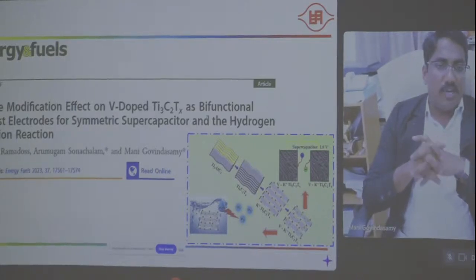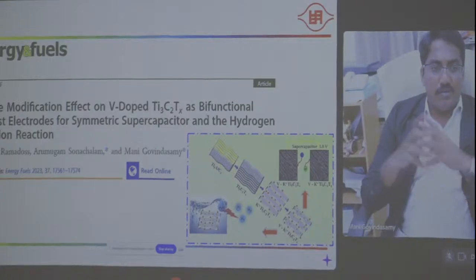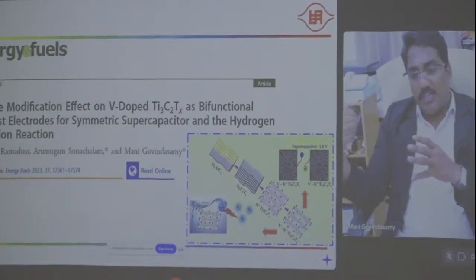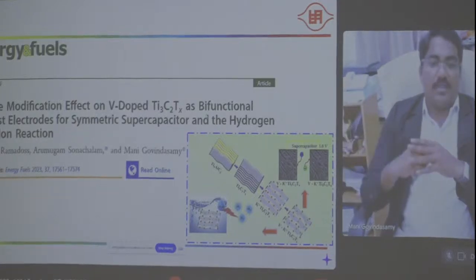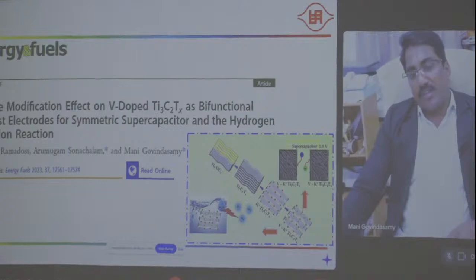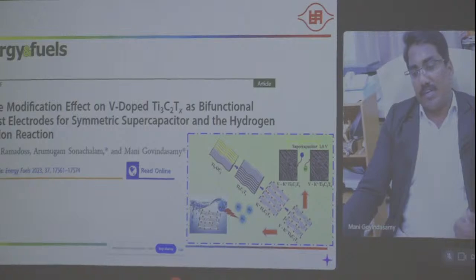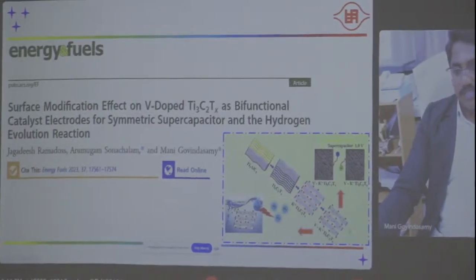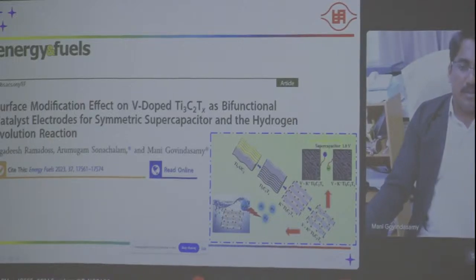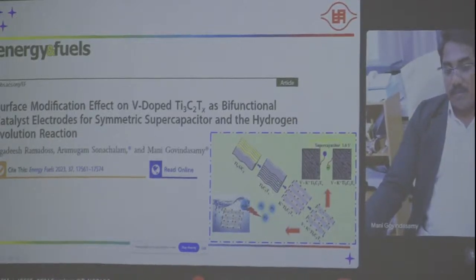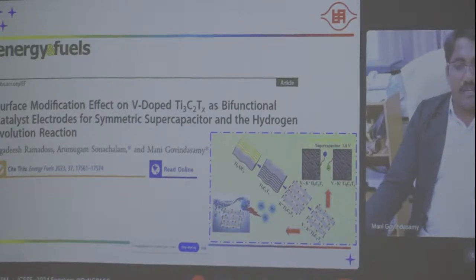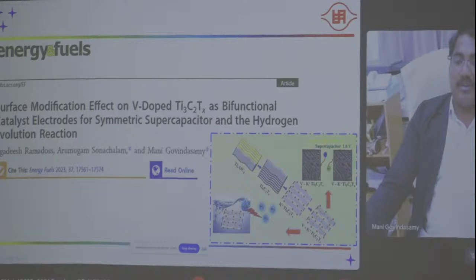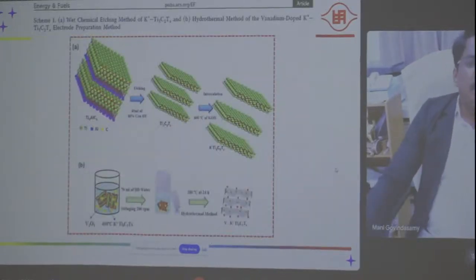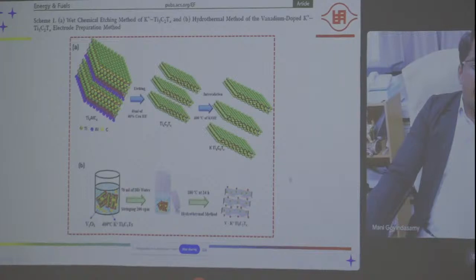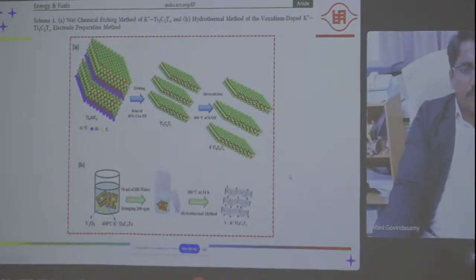The next one we developed is vanadium doped titanium carbide. The vanadium we can develop in situ in the MXene preparation. After we prepare the MXene from the MAX phase, we use potassium intercalation, then vanadium doping. Totally three processes will be there: MAX to MXene, then the intercalation process, and the next one the doping process. After this doping, we apply it for supercapacitor applications. These are the procedures we apply for the vanadium doping related materials.